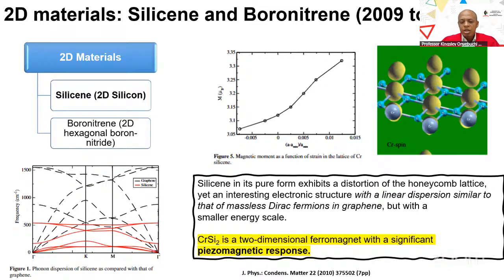But something interesting that we looked at was, can we introduce new atoms in this system? Can we dope this material? So in this case, we doped with chromium and saw how this material behaves. We studied a whole host of dopants. But one interesting thing we found is that doping this material with chromium results in a two-dimensional ferromagnet with a significant piezo-magnetic response.